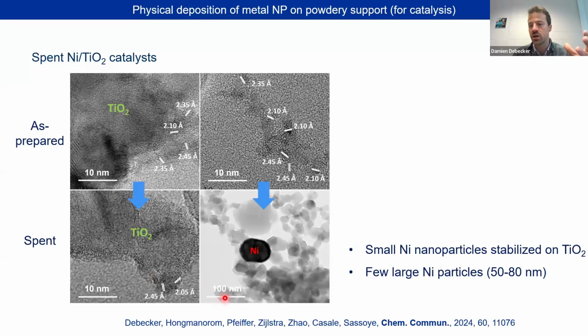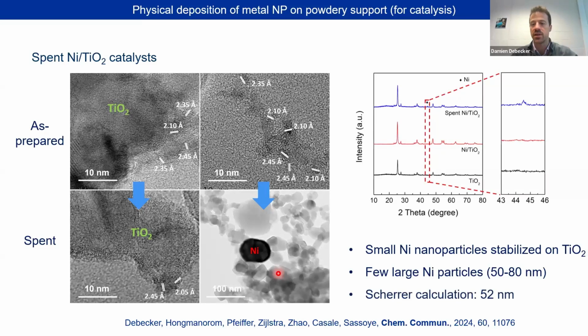But if we are careful enough, and I want to be honest with you about that, we did find in some very rare places huge chunks of nickel, which are of course not active, and these probably come from the floating nanoparticles we highlighted before. So that has to be improved, of course. They are also detected in XRD here.